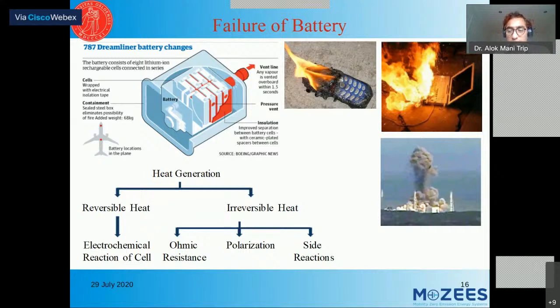And then we have certain side reactions. Basically, some component in the battery, when you use it, is reacting because of the very high potential. Like if you have a nickel-based lithium-ion battery, generally it works above 4 volts, and the present-time electrolyte is not supporting 4 volts. So we have certain kinds of reactions at the interface. That's called the side reaction. I'm not going to go into detail, just give you an example.